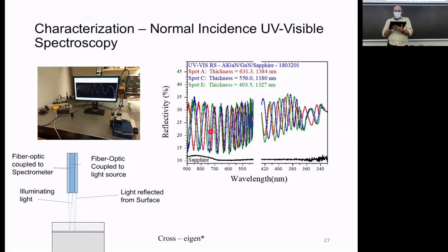And you can see here that we have these interference fringes. And this is very similar to something like Newton's rings, counting the rings up that you see in the interference pattern. That is basically what this is, except instead of using the same wavelengths of light, we're using multiple wavelengths with the same thickness and seeing how they interact with the thickness rather than changing the thickness for the same wavelengths.